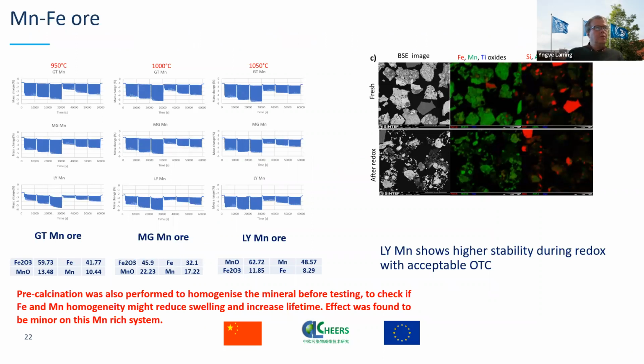For the manganese iron ore, we looked at 3 ores from China. The first two have high iron content, and the last one has high manganese content. The iron content shows very good capacities in one way, but the strength is very low because iron cations diffuse very fast at high temperatures. It gives swelling and very fast degradation, while the manganese ore showed better stability and still a decent capacity.